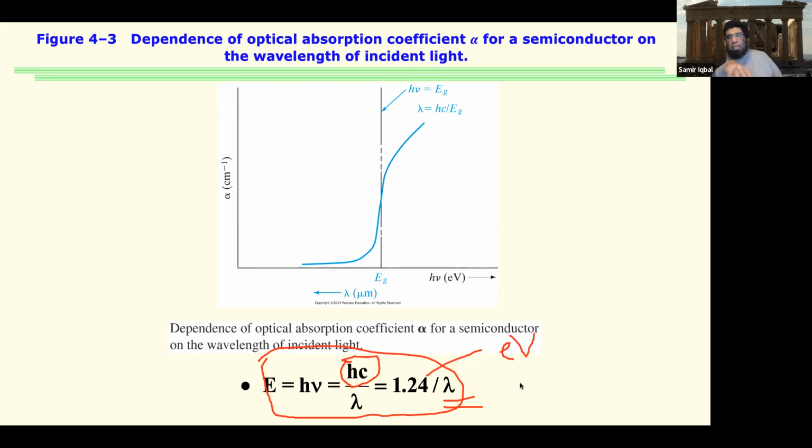From the wavelengths that get absorbed and those that get transmitted through, that edge tells us the band gap energy of that unknown material. You have to know that energy and wavelength are inversely related. So a higher lambda means lower energy, and vice versa.